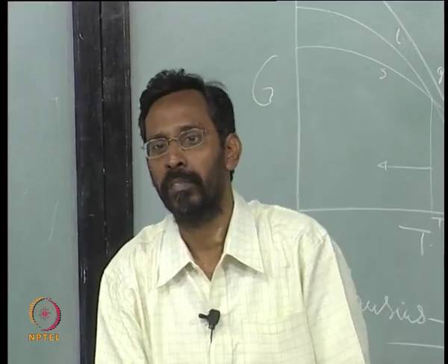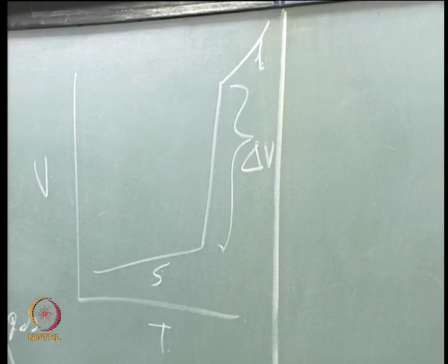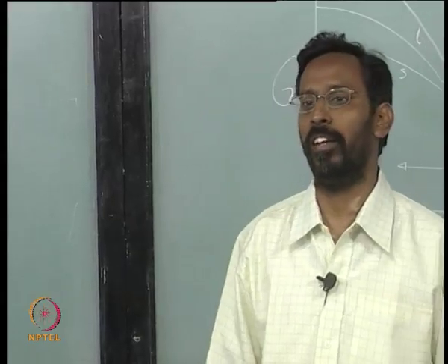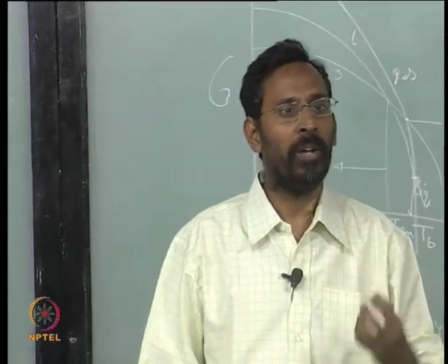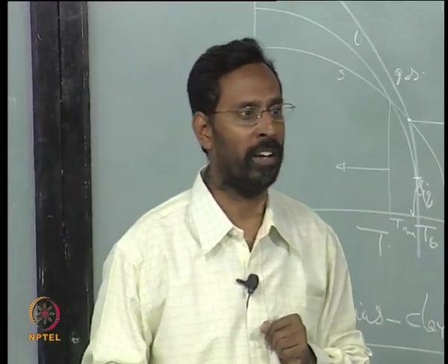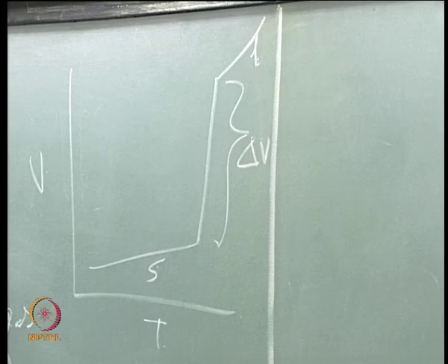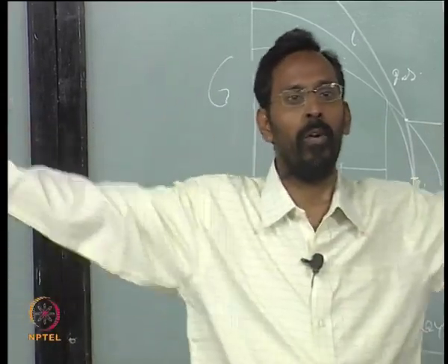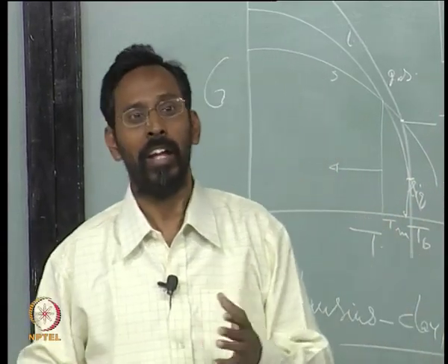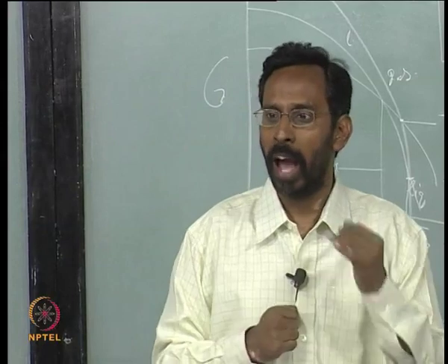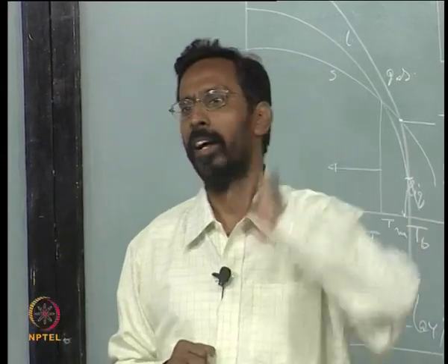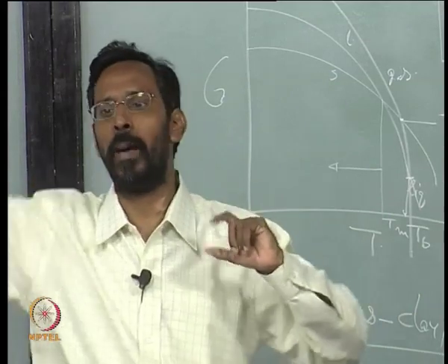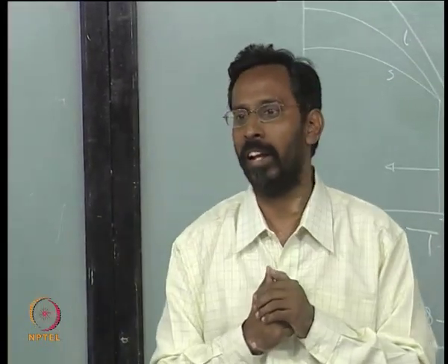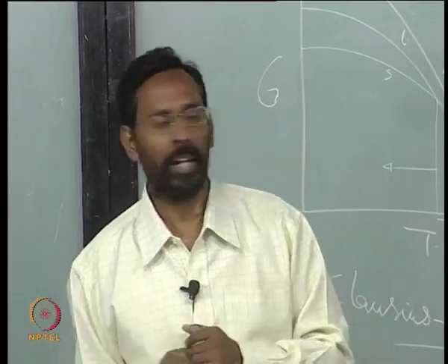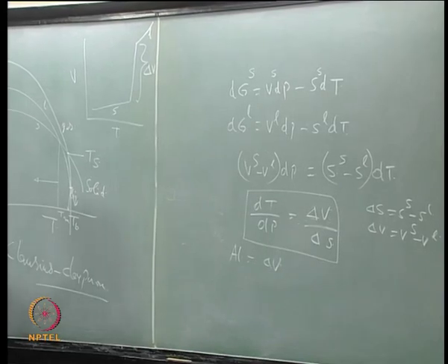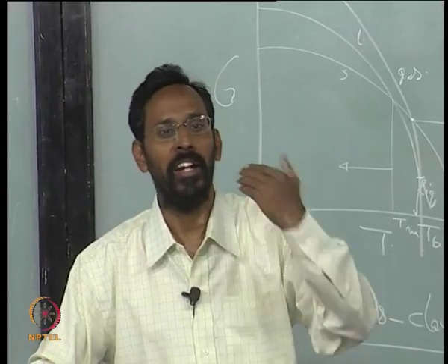Grey cast iron. Why is there no shrinkage in a grey cast iron? Yes, graphite has a lower density. In a grey cast iron, when the liquid is solidifying, you get gamma plus graphite during the solidification, and graphite has a much lower density than that of the iron. As a result, it occupies more volume, so there is a volume expansion. Depending on how much graphite is coming, you may have a lower shrinkage, zero shrinkage, or even an expansion, depending on the composition of the cast iron. That is why in some cases of grey cast iron we give what is called a negative allowance.